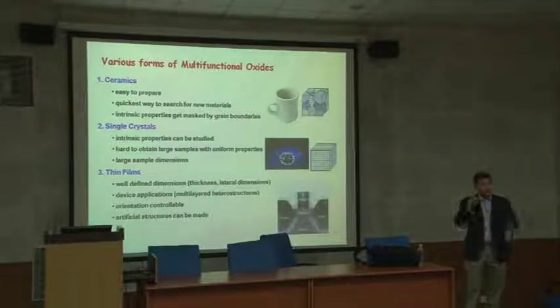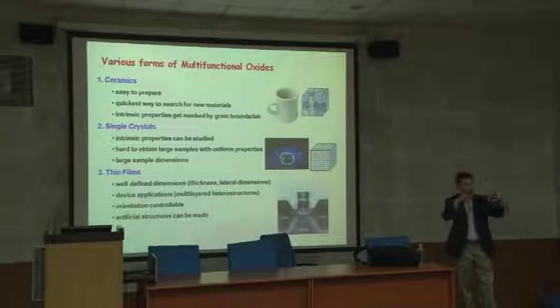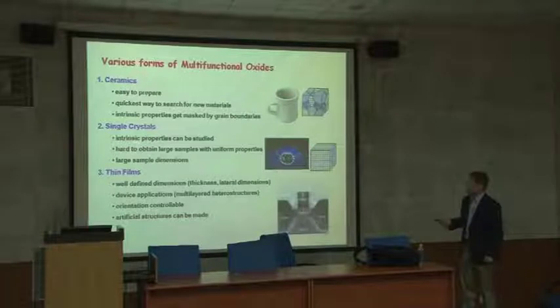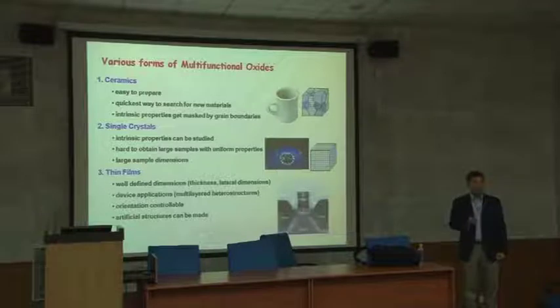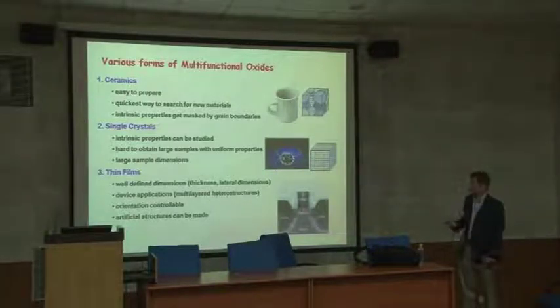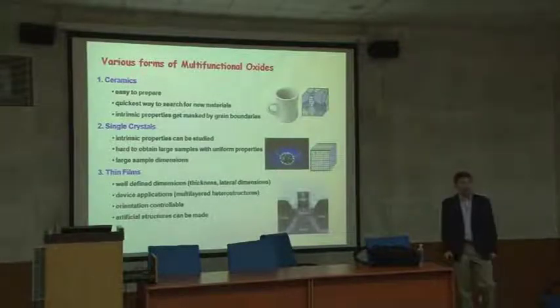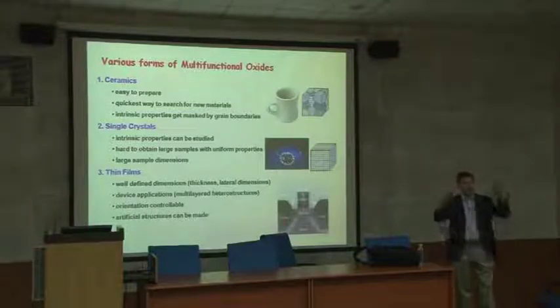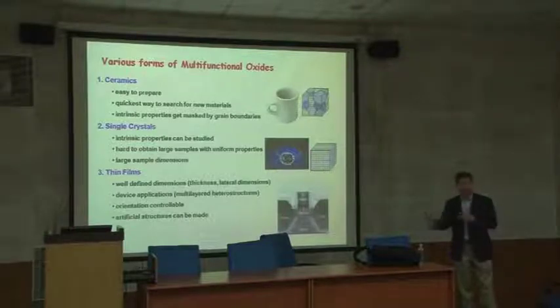And then all the atoms, it's a three-dimensional array, perfectly aligned. And that is actually an intrinsic property, anisotropy, without any defect, and then you can measure those important properties. And then the problem here is, anybody can find a blue diamond bigger than this? Very hard to make diamond big. And same thing for these complex oxide materials, hard to grow large size crystals.